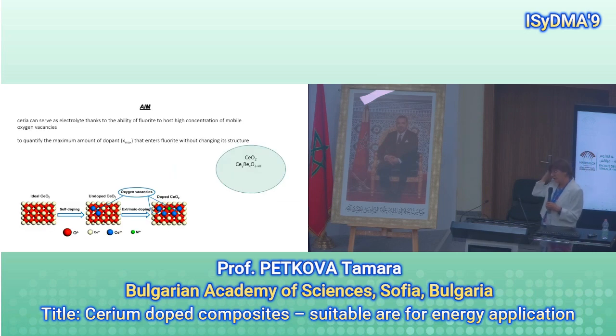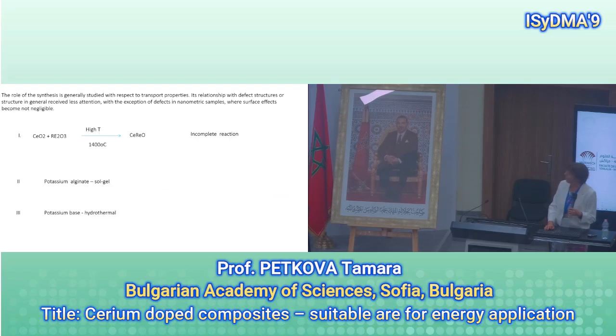So we decided to find how the structure of the cerium oxide changes if we dope it with gadolinium, and to find the amount of gadolinium which we can introduce without changing the fluorite structure, which is good for the application that we expect to study. Therefore, we started with the synthesis of our materials.